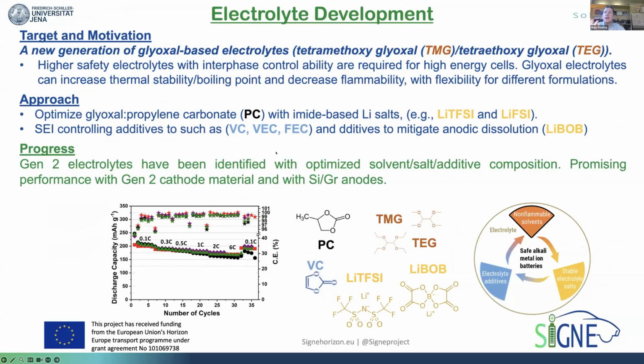On the electrolyte side of things, so again, as I mentioned, it's around these glyoxal-based electrolytes. So we have had lots of issues that we needed to address here in terms of the cathode compatibility, but also the anode compatibility. We had some side reaction issues with cell components, for example. So what we've been able to do through the partners who are University of Jena and Solvionic is identify ideal electrolyte components and compositions that are compatible with our cathode materials, and also with our anodes. Okay, so there was lots of nice electrolyte design that went into this, finding the correct electrolyte additives that would allow us to deliver this type of stable cathode performance that you see here, for example.